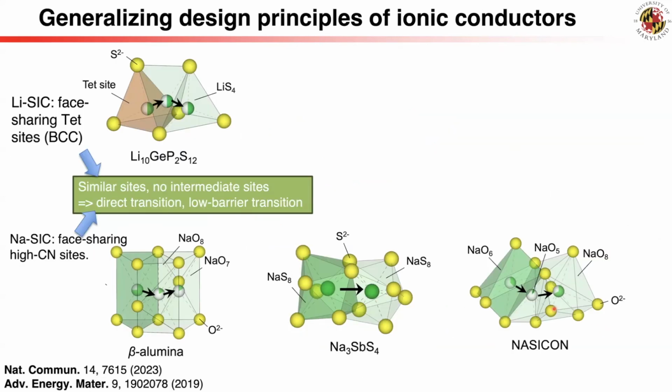So with our work, we established the face-sharing high coordination site as a design principle for sodium superionic conductors. In addition, we can also generalize this understanding. Why sodium-ion conductors work is that they provide a favorable site for sodium, which is a high coordination site, and their face sharing provides no intermediate site and a large bottleneck that gives a low energy barrier.